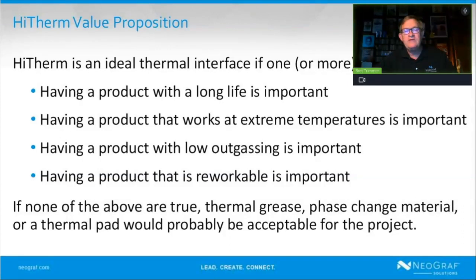Having a product that works at extreme temperatures is important. Again, some of the devices out there run at over 200 C, which is no problem for the graphite. However, greases and phase change are pretty much at their limit. If you need a product with low outgassing, our products are just graphite. There's nothing else in there other than graphite. And so the material does not outgas. This is important for several different industries, and we'll talk a little bit about that when we talk about satellites and LEDs. And then having a product that is reworkable is important.